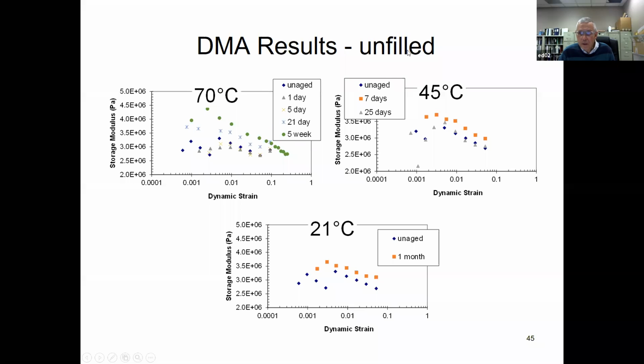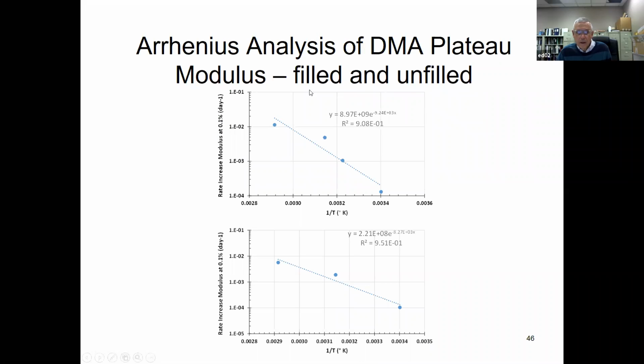And then here are our DMA results for the unfilled compounds. Here's unaged, 1 day, 5 day, 21 day, 5 week. And then here's the data for 45 degrees and 21 degrees. And here are our Arrhenius plots for increase in modulus at 0.1% for the filled compounds. And here's the rate of modulus increase at 0.1%, plotted on an Arrhenius plot for the unfilled compound. And again, we see no evidence of mechanism change.